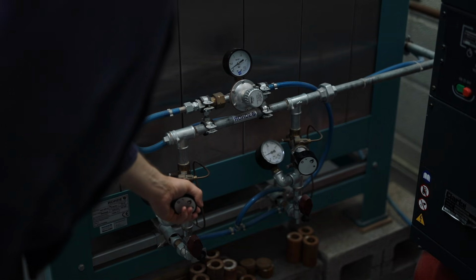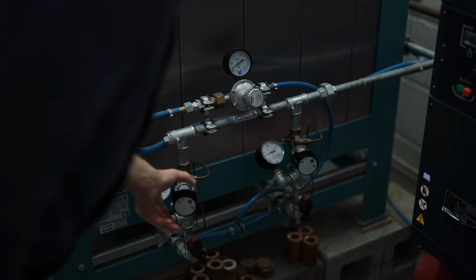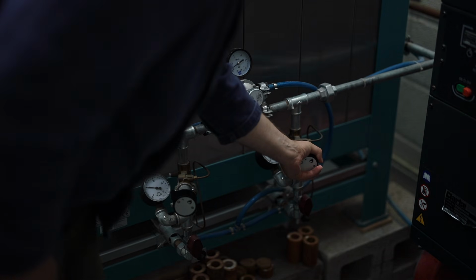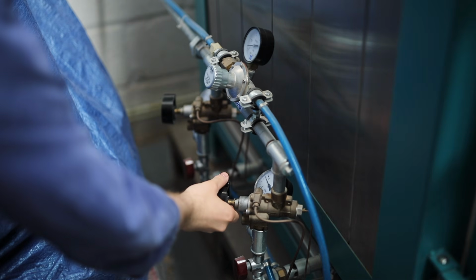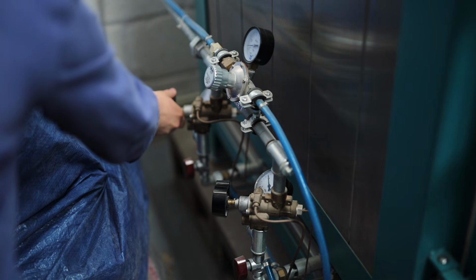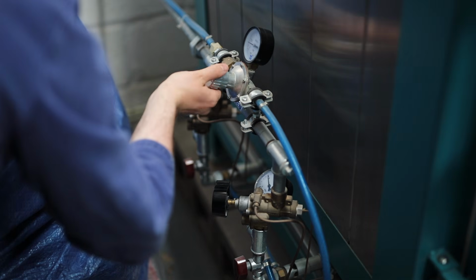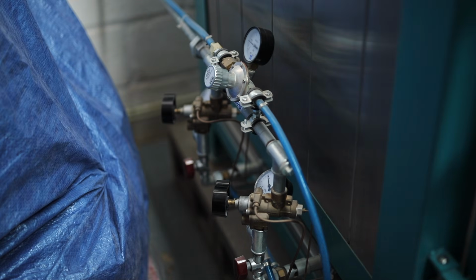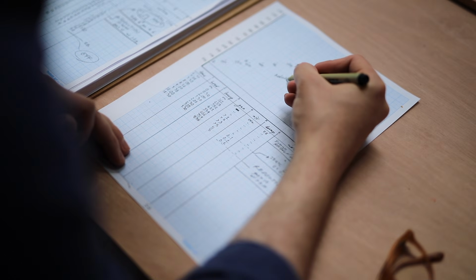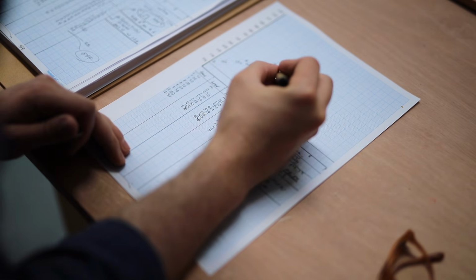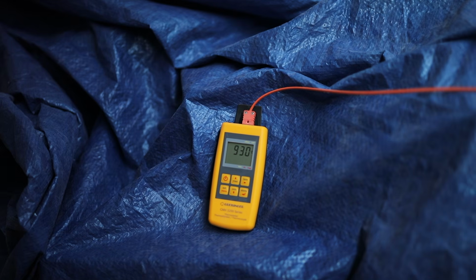This creates a state within the chamber where there's too much fuel and not enough oxygen for it to burn properly. As a result, and as this atmosphere is seeking oxygen, it ends up stripping it away from the clay and glazes themselves, and it's this that creates the distinct blue and green colour of Celadon glazes, as the iron these types of glazes contain is chemically altered as oxygen is taken away from it.